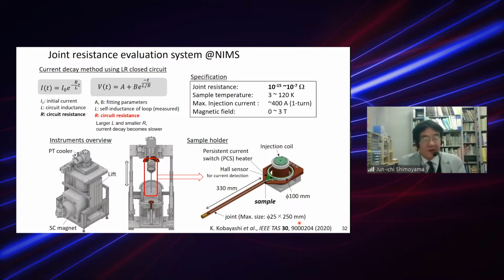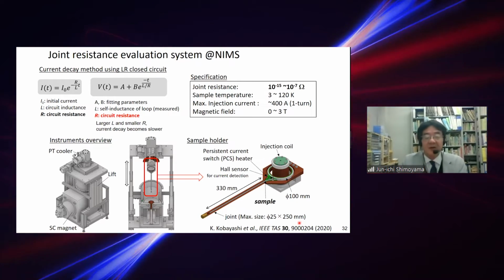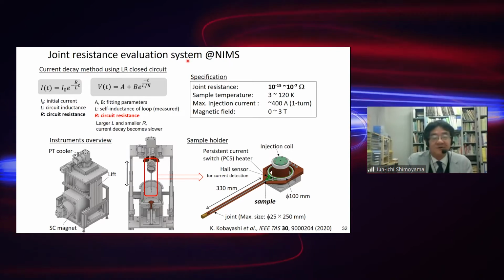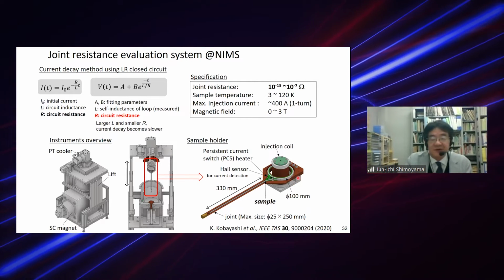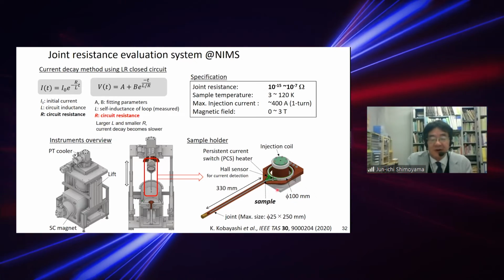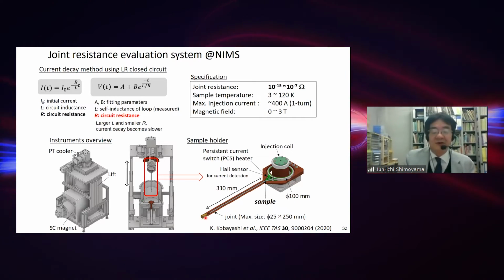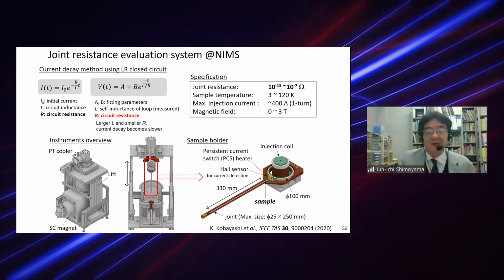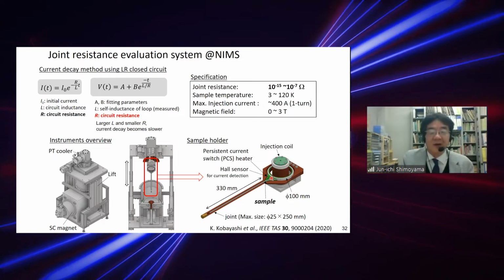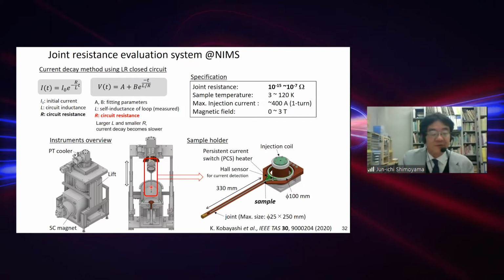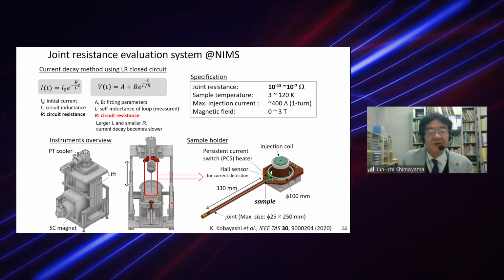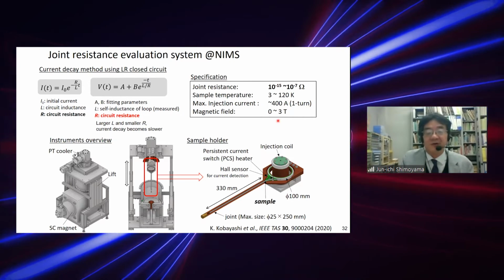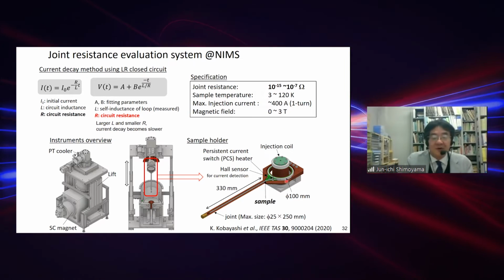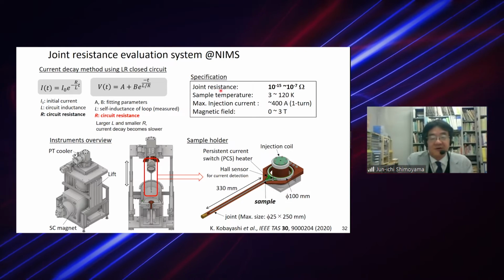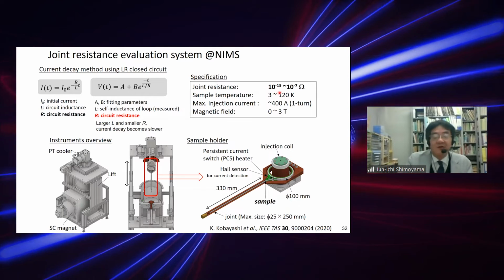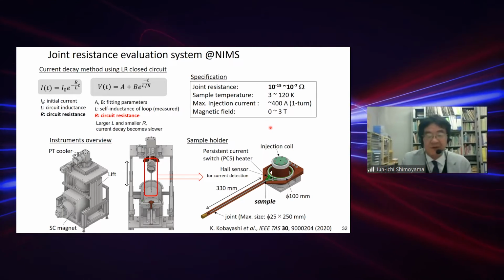So to evaluate joint performance more precisely, NIMS developed the joint resistance evaluation system. This is a very sensitive system, as you see here. This is the injection coil, and this is the coil, and the joint exists here. So in this case, the Hall sensor is located here to detect the current decay. If we put the joint part into the superconducting magnet, we can measure joint performance in the magnetic field up to 3 Tesla. With these systems, we can evaluate the joint resistance down to 10 to minus 15 ohms. This is a very, very sensitive method.